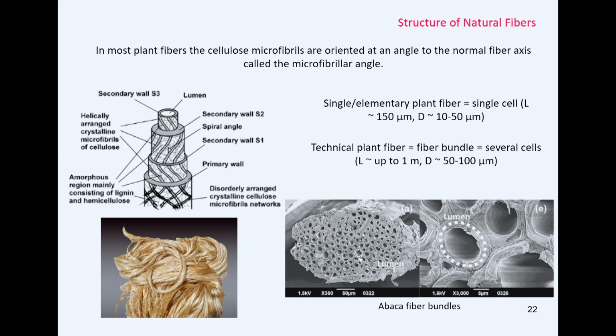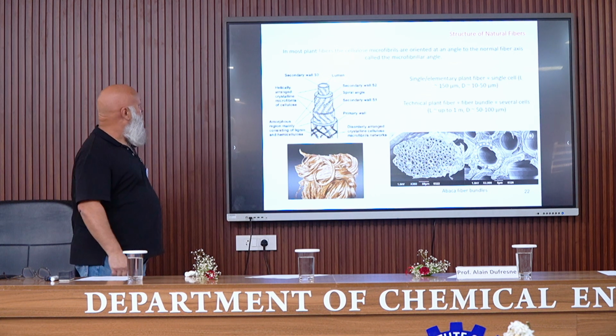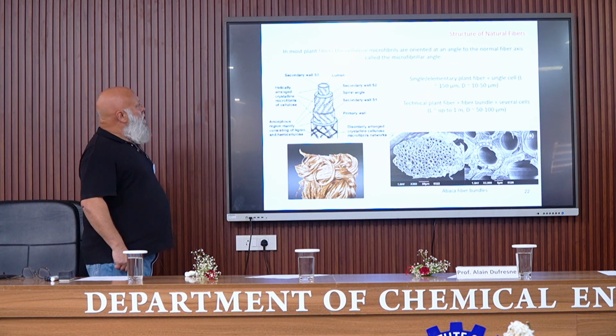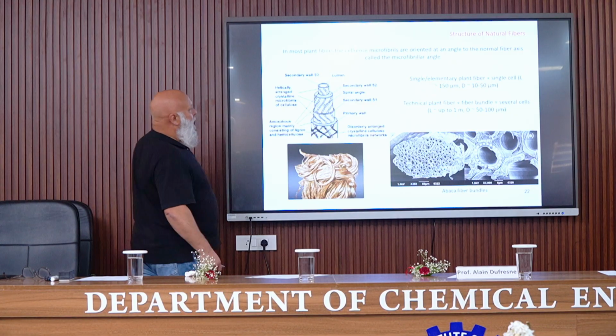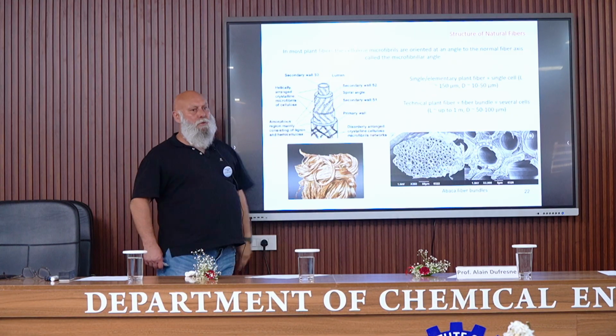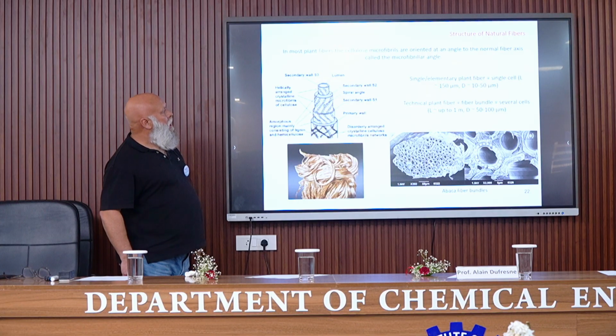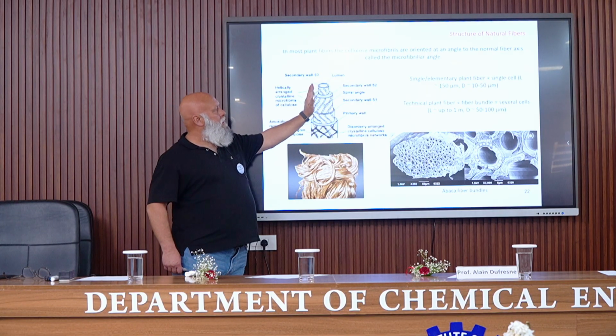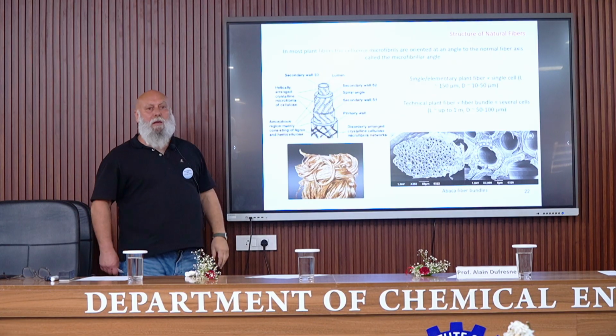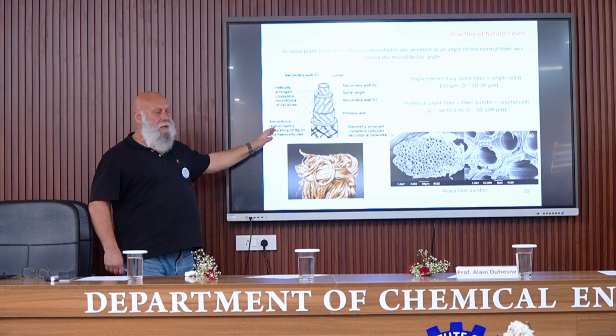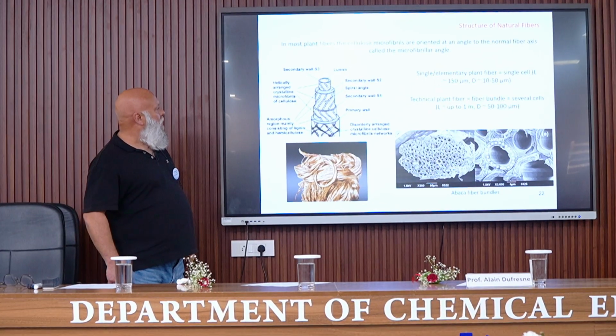So I come again to this representation of the natural fibers. I didn't mention previously that you can see there is a hole in the middle of the fiber, which is called the lumen. And this lumen is necessary to transport water in the plants. In most plant fibers, the cellulose fibrils or microfibrils are oriented, at least in the secondary walls, at an angle to the normal fiber axis, and this angle is called the microfibrillar angle. And we'll see later the impact of this microfibrillar angle.